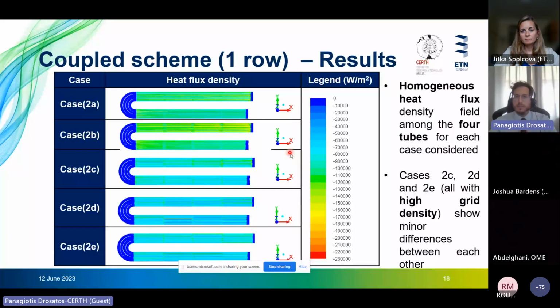Here you can see the developed heat flux density field as derived by the numerical simulations. You can see that indeed this specific parameter is developed homogeneously among the four tubes for each specific case considered. And the slightest differences are spotted among the last three cases, which are characterized by very fine numerical grids.